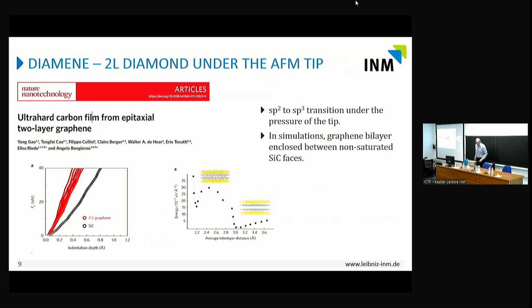Then there was a paper by Elisa Riedo's group, and Angelo was also involved. What they said is that if you press with an AFM tip, the pressure you apply to the graphitic system is high enough to induce, by pressure, an sp2 to sp3 transition. So essentially, you make diamond under the tip for a short time. But you need the hard silicon carbide surface to do that. And they also found in the DFT calculation, in the lower right panel here, that there's actually a minimum. So if you press this together, you will drive the system over a barrier into this diamond state where it will rest. But note that here, the yellow stuff, which is the confining silicon carbide, is not saturated with any bonds, which will become very important.